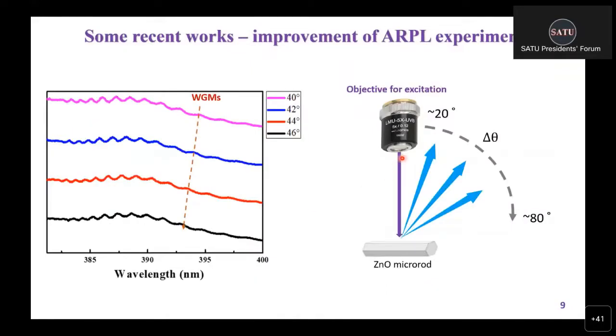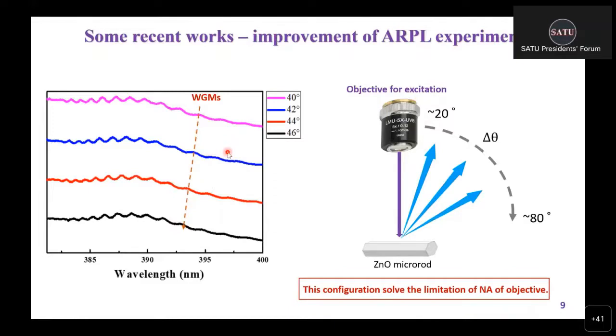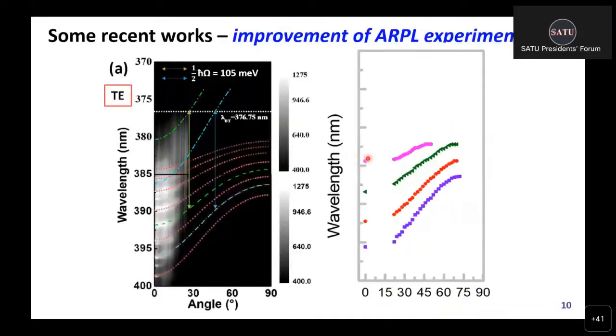So we directly measure the spectrum at different angles by fibers. We observe the mode shows blue shift tendency. And if we plot the trajectories of these modes, we can obtain figures like this one.